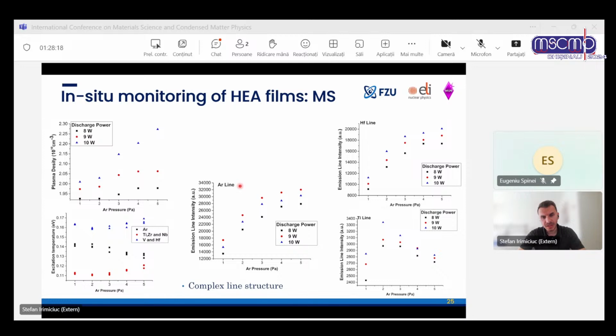But we also did some calibration of the deposition with this optical emission spectroscopy. And what we managed to do is actually to show that for titanium, there is a significant problem, and there's an optimum where we don't lose titanium anymore. If we add more argon pressure, the film will be titanium deficient, which we saw from our previous experiments, but now we can see it from the optical emission spectroscopy. And when we look at the density, there are obviously two discharge regimes, with the optimum being 2 Pascal of argon. And this is what we used for the deposition.